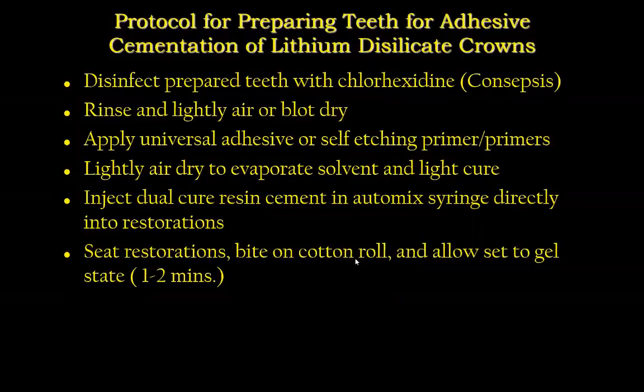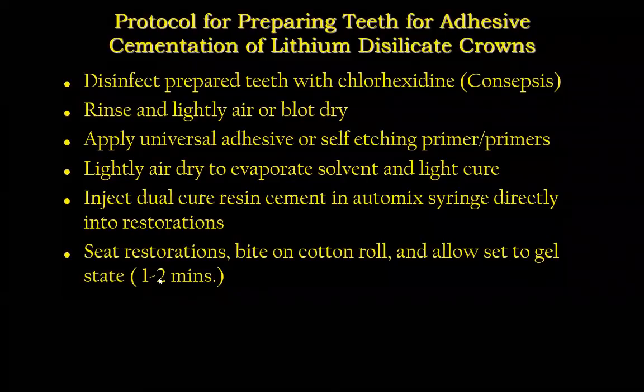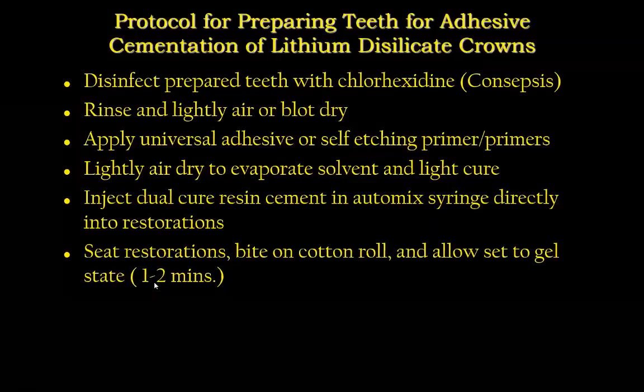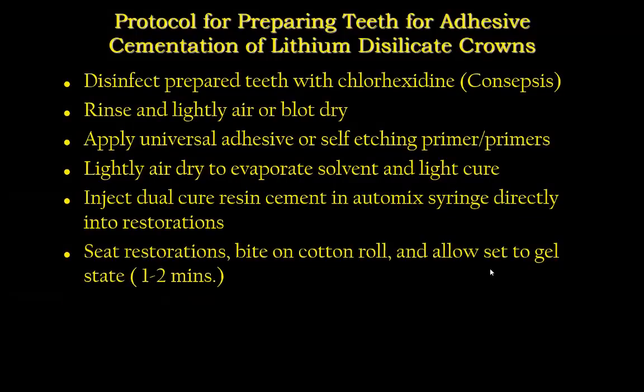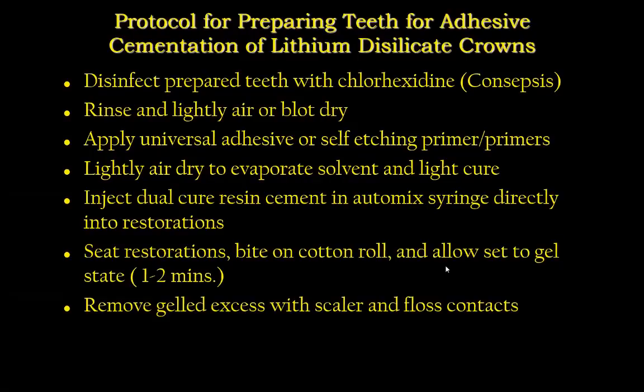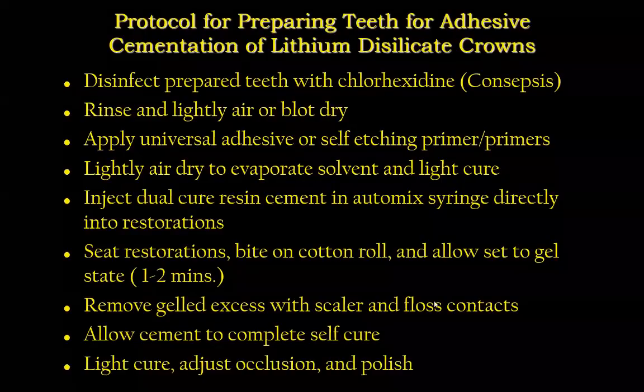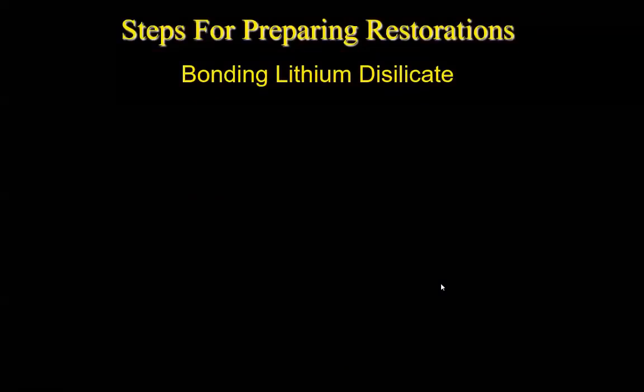I seat it, I have them bite on a cotton roll. You can allow it to gel set, or I do the flash cure, 1 to 2 seconds, clean it off, or the gel set usually occurs in 1 to 2 minutes. I just don't like to wait because I have to keep feeling it to see if it's gel yet. So I do the flash cure, have them bite back on the cotton roll, wait another 2 to 3 minutes. Then I light cure first in the gel state, I clean the excess and floss the contacts, then have them bite on the cotton roll, allow the cement to complete self-cure. Then I light cure facial, lingual, and occlusal, adjust occlusion and polish.